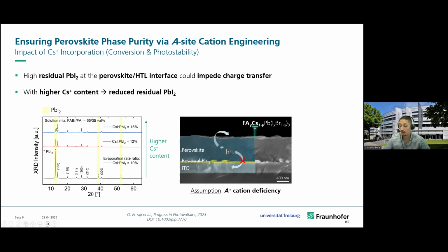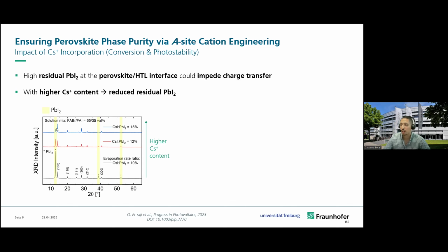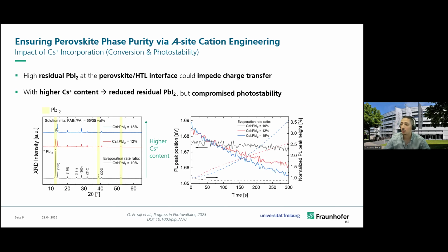How does this reflect in terms of the optoelectronic and the photostability of the film? We carried out photoluminescence measurements, and here we see the evolution of the PL peak position and the PL peak height over the duration of laser illumination. So you can see that when we have a high cesium amount, so for example here the curve in blue, you can see that under laser illumination, there's a high deviation of the PL peak position, which shows us that we have halide segregation and our perovskite is not photostable.